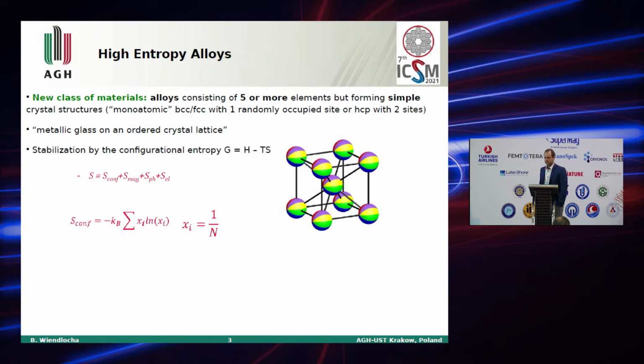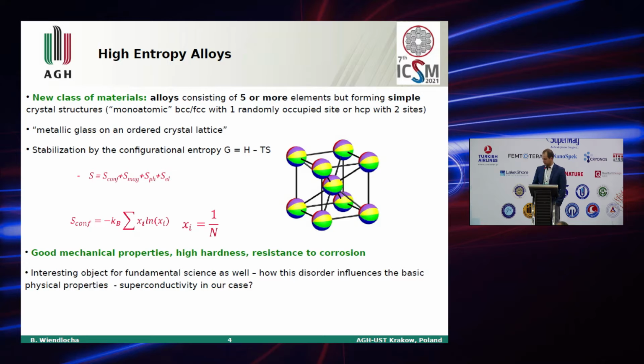And the reason that they form such simple structures is the stabilization by the configurational entropy term, which enters the free enthalpy of the material. So they are sometimes called metallic glass on an ordered lattice. So the crystal lattice is ordered but the chemical disorder is induced by the different elements occupying the same site. And they have been studied for a couple of years because of their good mechanical properties, but also they are interesting in terms of the basic physics, how this large disorder influences the basic physical properties like superconductivity in our case.